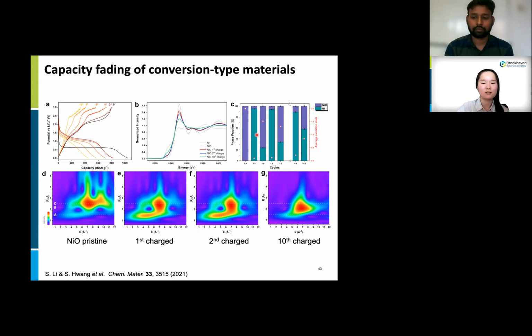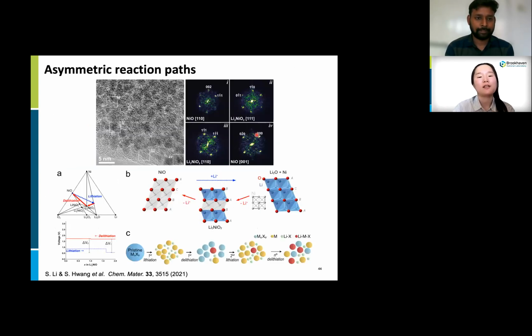Even after charging, we got high resolution TEM images to figure out what really happened inside at the nanoscale. And even though lithium is extracted, we found nickel and nickel oxide phases. And we found that incomplete lithium removal is strongly related with these intermediate phases. And these intermediate phases pile up as cycles go, and eventually we lose the available lithium ions and capacity degrades.